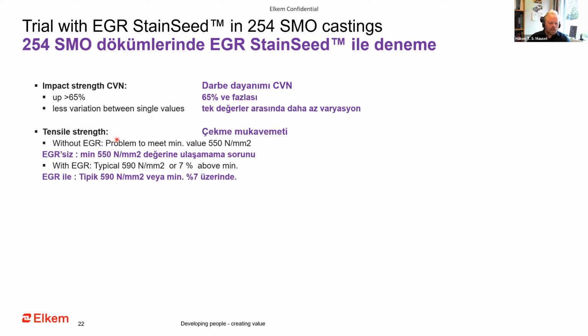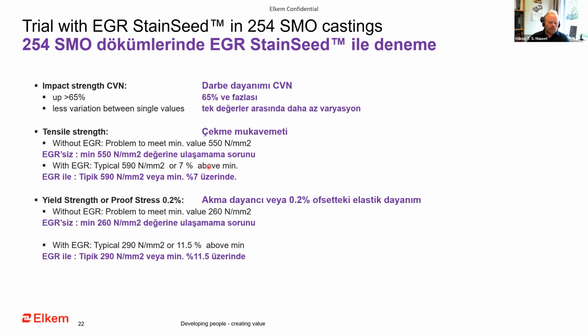With regards to tensile strength, when they didn't use EGR, they had problems to meet the minimum value of 550 megapascals. But with EGR, they typically achieved 590 megapascals, so more than 7% above the minimum requirement. The yield strength, they had a problem to meet the requirement of 260 megapascals, but with EGR, they achieved 290 megapascals, so 11.5% above the minimum requirement.